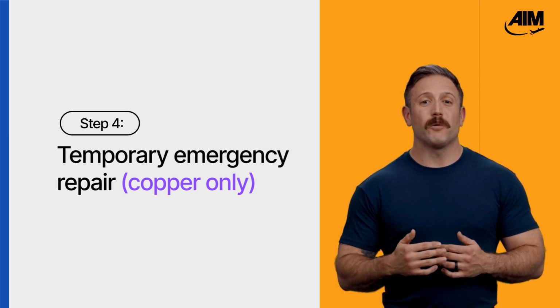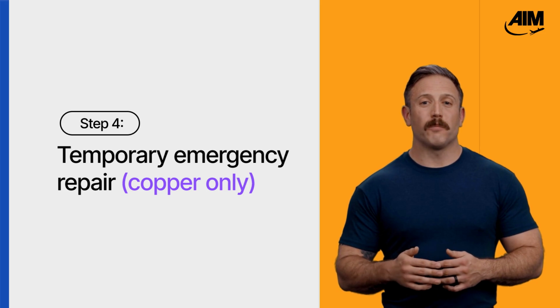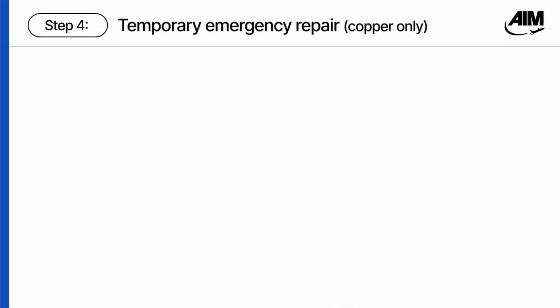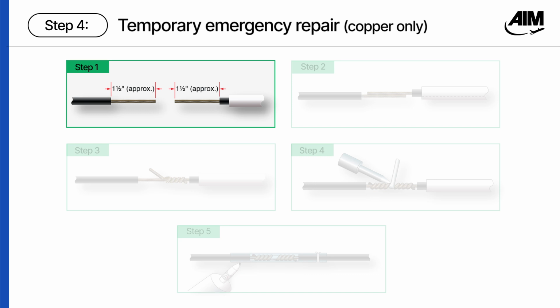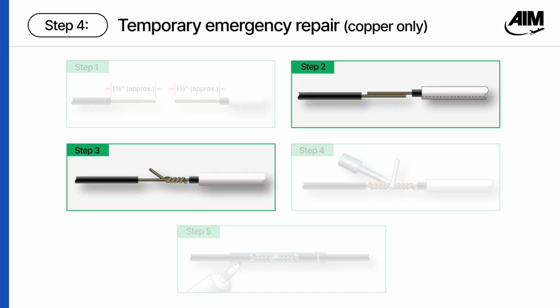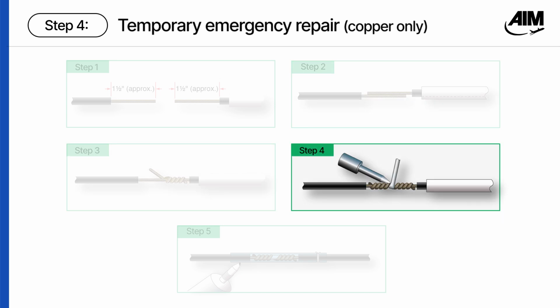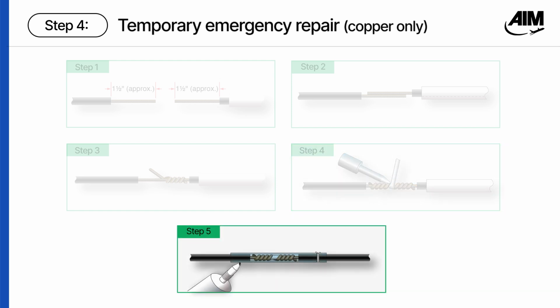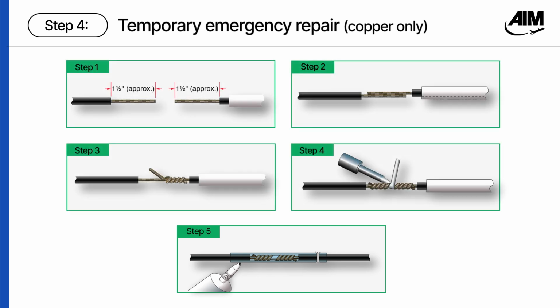But what if you don't have a terminal available? If the wire is copper, you can make a temporary emergency repair by stripping about 1 1/2 inches of insulation from each end, twisting the bare wires together, and soldering the joint using 60/40 tin-lead resin core solder. After soldering, slide the correct size heat shrink tube over the repair. Apply heat on the shrink tube until the tube has covered the repair. Keep in mind, this is a temporary repair, and always refer to the specific aircraft manual for direction. Not all aircraft manufacturers will allow this type of temporary repair.